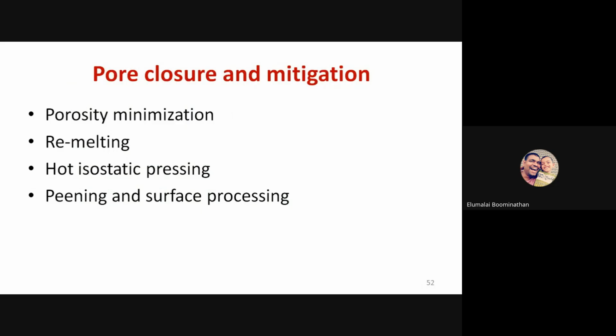when using the SLS process. As I said earlier, you have to optimize the laser power and scan speed to achieve stable melt pools, and preheat the powder. So the supplied powder should have a base temperature. Preheating is sometimes necessary to get the appropriate thermal gradient, and you need to use a smaller and more uniform spherical powder. The smaller the powder, the denser it is, so better packing will reduce the porosity effect. And remelting sometimes, so melt the layer again, will help in densifying the layers.